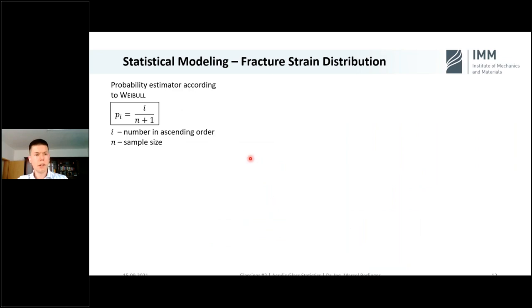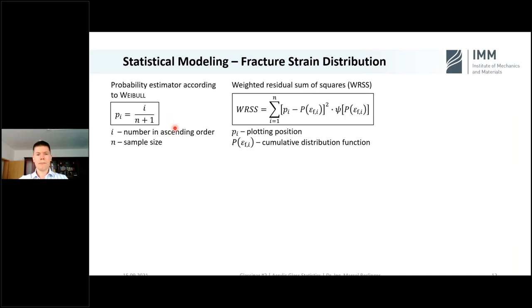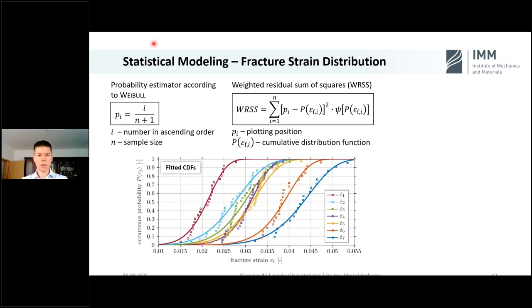So a few words on the fitting of our functions. The probability for each experiment was assigned by the Weibull probability estimator according to this formula. Fit criterion was a weighted residual sum of squares. Deviation between experiment and CDF was minimized. For more detail, please check out our paper. There it is explained more in detail. And so for our 7 samples, we got 7 CDF functions fitted here, each in the same color as the experiments.